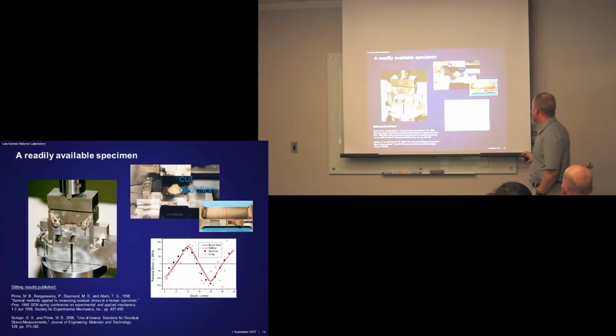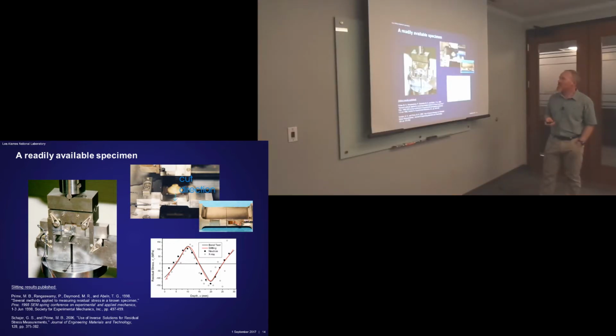Red line is the slitting result. We did neutron diffraction and X-ray diffraction, which we did kind of along the surface there, which is noisy because this thing had pretty big grains in it, but they all match. So a very well characterized specimen. Know what the stress is.